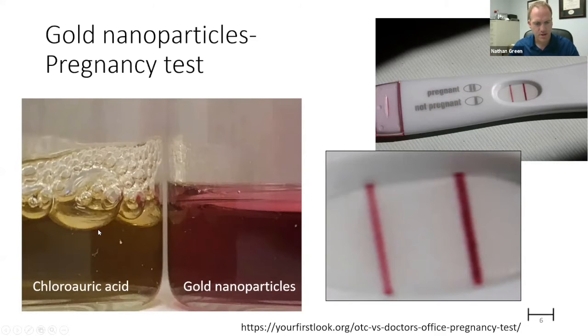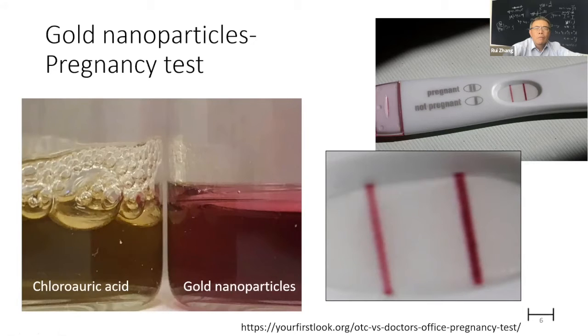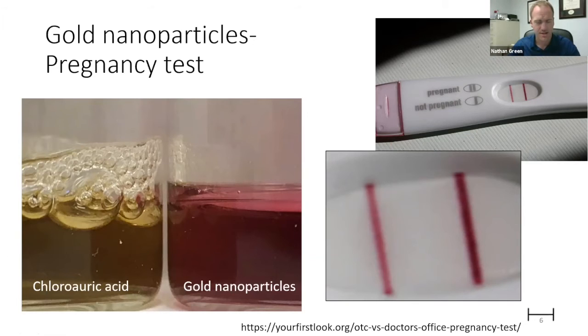But as we reduce that chloroauric acid, gold 3, into gold 0, it turns into nanoparticles, and you can see that red color. And I put these side by side so you can hopefully see the red color shared across these pregnancy tests. Now, that doesn't mean that we need to go and buy up pregnancy tests and get the gold out of them. A very small amount of gold nanoparticles are very highly colored, and so the amount of material you need is negligible, but it's mainly because the color stays so well.